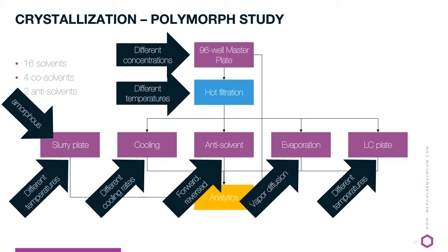Addition rate can be changed as well as the amount of anti-solvent that you add. In evaporative crystallization, you should consider a vapor diffusion as well. This is not scalable, but it will show you in certain cases a different form that is available. And it will give you indication how do you do your drying. Quickly remove everything under high vacuum, use a nitrogen feed to your material to improve drying, or just leave it and let it crystallize in the vapor that is actually there.